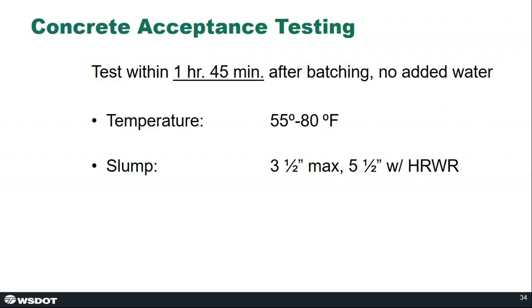Second, we test for slump. We have a 3.5 inch max. Unless they use a high range water reducer, we allow up to 5.5 inches of slump. And there's not a great correlation between slump and durability. We're kind of moving away from the importance of slump. However, it still remains a good indicator of consistency from batch to batch or day to day. It can flag something wrong with production or batching or delivery or pumping.